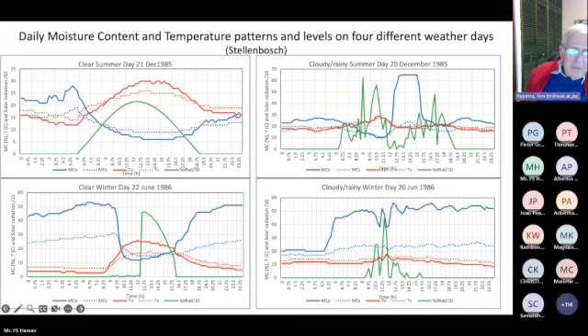If we compare that with winter, on the left bottom side, the clear winter day, the moisture content levels are quite high during the night or early mornings, and it goes down when the sun comes out. That is a bit of an error in the insolation measurement, and then it goes up again when the sun is set. And on the right-hand side, the cloudy, rainy day, most of the time it's far above 40% moisture content.